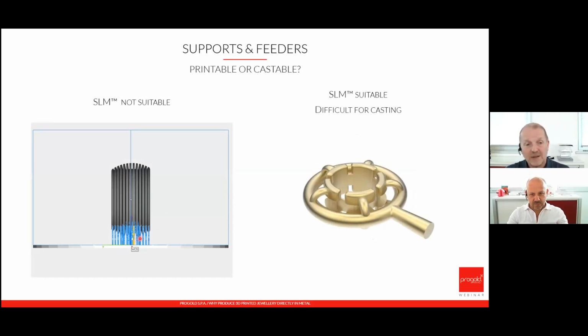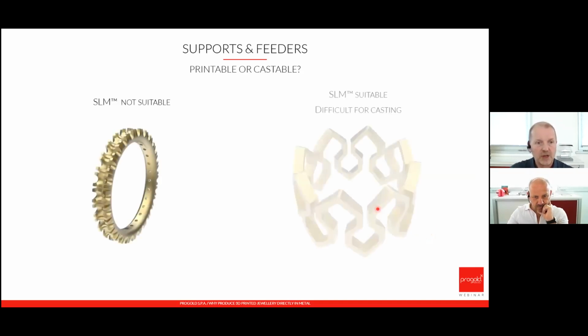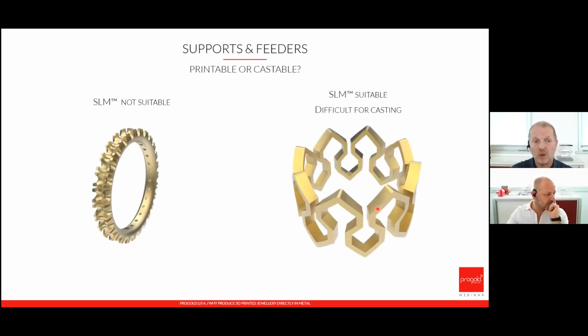Supports are difficult to remove in this case, and are in a very tough position to be removed and to be polished, okay, to allow polishing of the part. In this case, instead, we think that the feeder system to cast this part is quite large and important. We have got another example of SLM not suitable geometry. This ring, the traditional 360 degrees ring, simple ring with stones. Okay, and on the right, a part that we judge very suitable for 3D printing and probably difficult to be processed by casting.